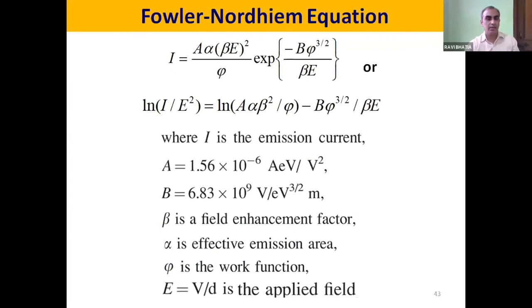So field emission studies are in corroboration with the equation called the Fowler-Nordheim equation, in which the most important factor is beta. Beta is called the field enhancement factor. I will try to explain it. You are actually applying a field of say 100 volt, and due to the geometry of your field emitter, and other parameters such as its diameter and size, for example, a carbon nanotube having 50 nanometer diameter will see this 100 volt field such that it becomes 10 to the power 9 volt per meter.